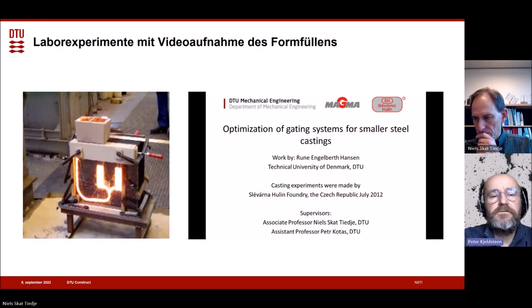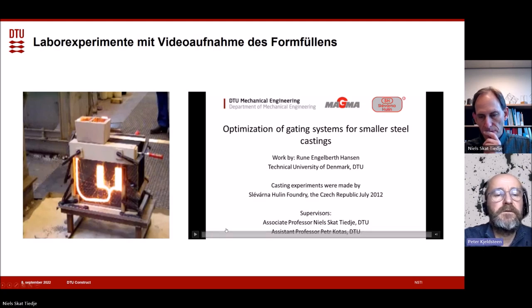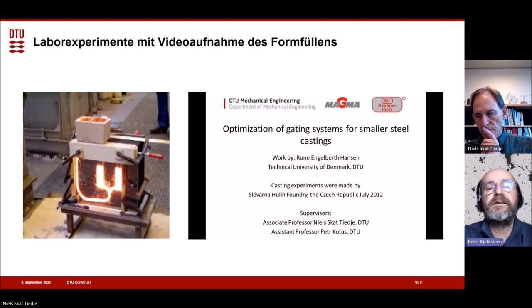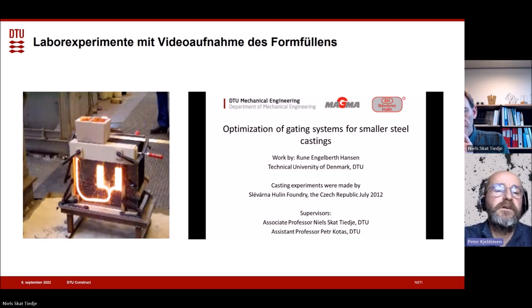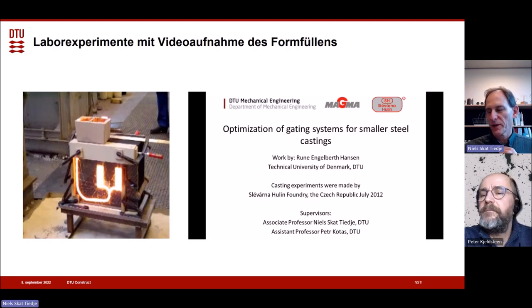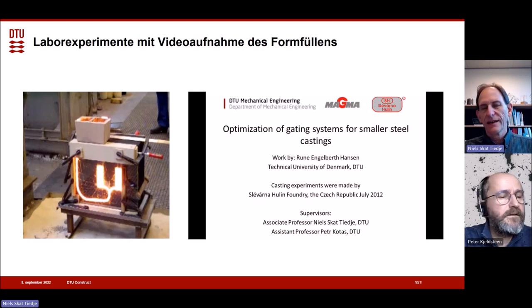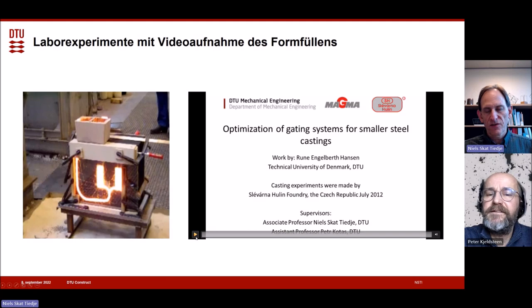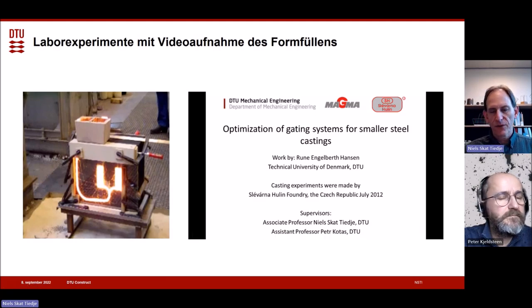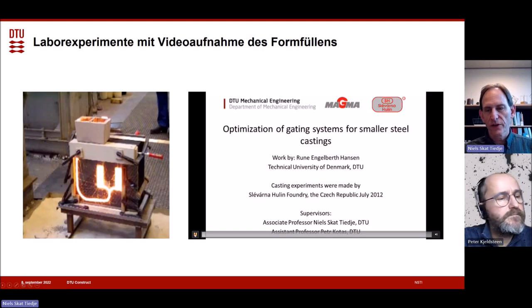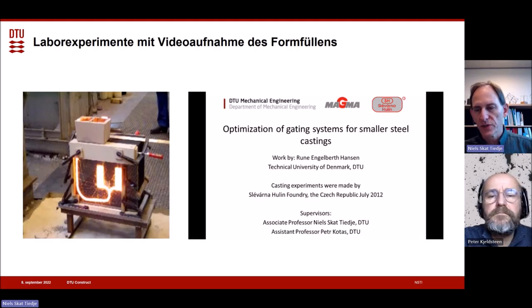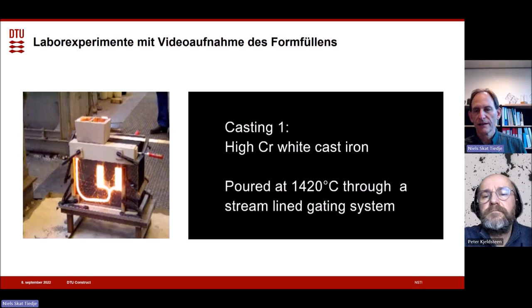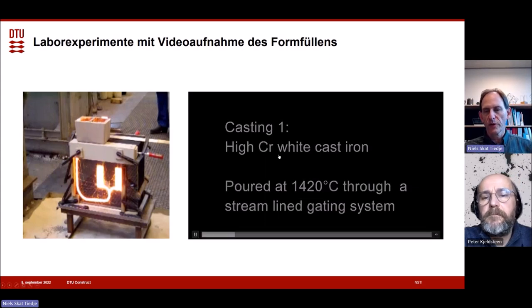In this trial, did you also calibrate this, or did you make simulations and then calibrate these simulations with the video you show? We did it the other way around. We actually did the experiments and then went back and modeled it to see how close we could get. There are two things: there's temperatures and there's flow. For temperatures, I can show a short video one of my master students did many years ago in the Czech Republic. We cast high chromium white iron.